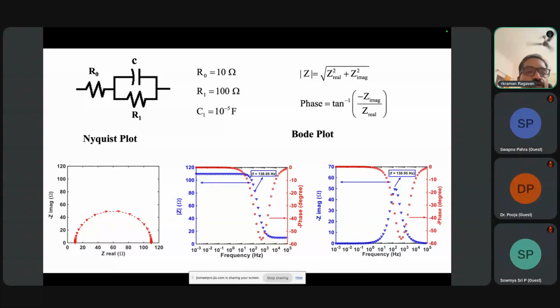Therefore, the value that you see here for this particular circuit is the sum of R0 plus R1. What is R0? 10. R1 is 100. The addition is 110. So you see 110. So the diameter of the semicircle is related to R1, and the initial point of the semicircle is related to R0. The final point is the sum of R0 and R1. And this particular frequency at the top of the semicircle is called the characteristic frequency. So from there we can calculate the time constant.